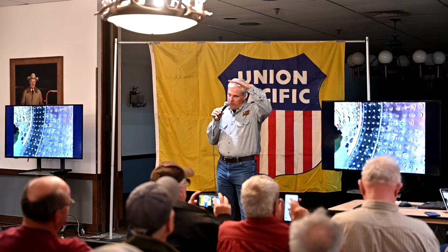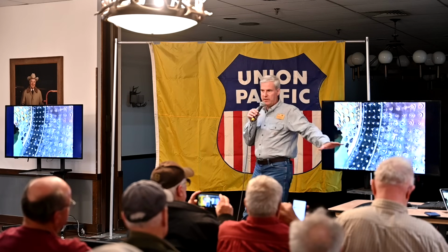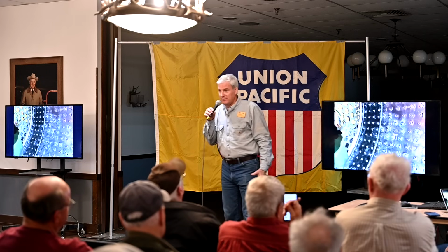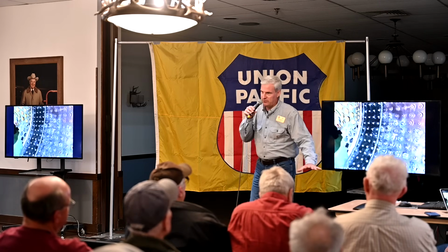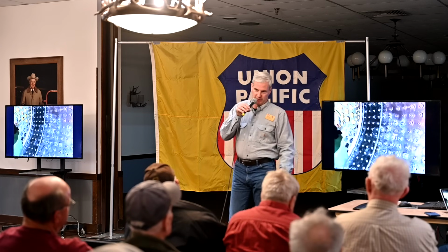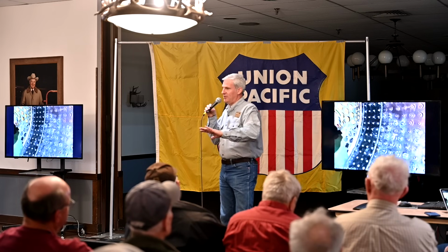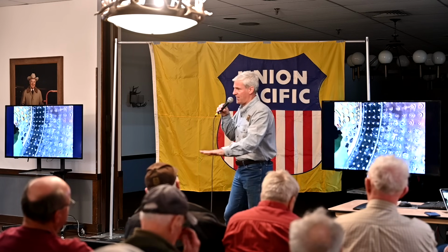But there was a small little leak in the smokestack, and the water came through there, and there was still a little bit of ash and debris in the firebox from when they used it last. Well, that water combined with the ash forms all kinds of things, and part of the stuff that's in water with coal, like your barbecue grill, is sulfuric acid. And it slowly, over the decades, starts melting that steel down.